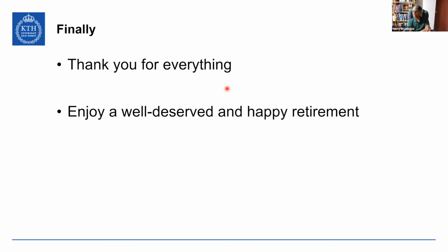I haven't. But you didn't actually mention anything about the really nice work that you did on the tetragonality. One of the big things that came out of my research was a bit of an aside from the industrial application: we found during some very careful analysis of the synchrotron and neutron data that actually it seemed as though the bainitic ferrite was not cubic. It was tetragonal. And this was something that is very easily explained.